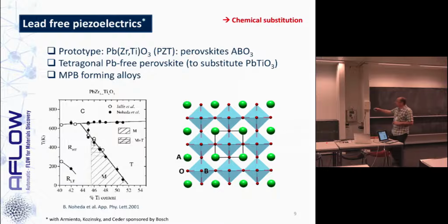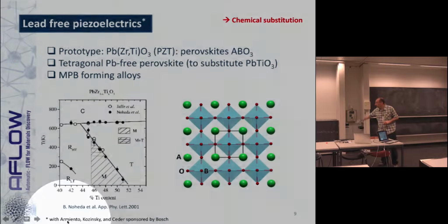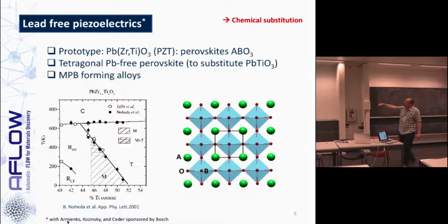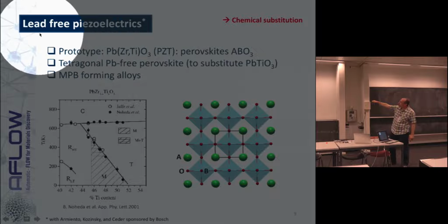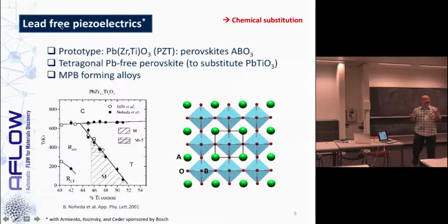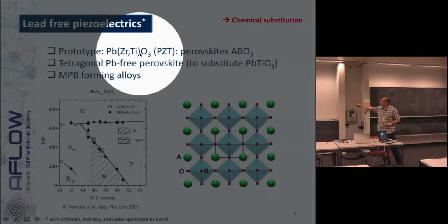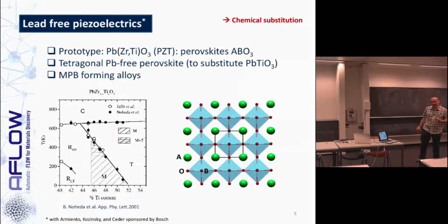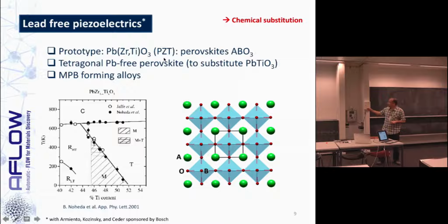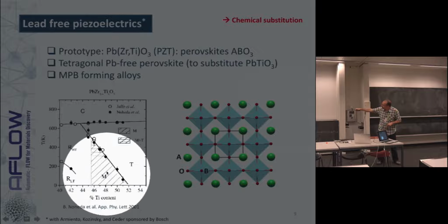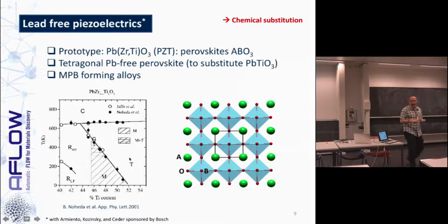So we did that long ago. This is a work in collaboration with Ricardo Armiento, Boris Kozinsky and Gerbrand Ceder, and we did it long ago. Our task was to replace lead in piezoelectrics. Okay? So we had constraints given by the company that was funding us, Bosch, and they wanted us to work on perovskites in order to mimic the property of PZT, that is a solid solution between lead zirconate and lead titanate. So what we did is try to set up a high-throughput calculation that could provide us with a new tetragonal system and a counterpart without lead that we can use in a phase diagram to create the region between the rhombohedral and tetragonal phase that is called the morphotropic phase boundary. So we have two tasks here, finding a tetragonal material and finding a morphotropic phase boundary.